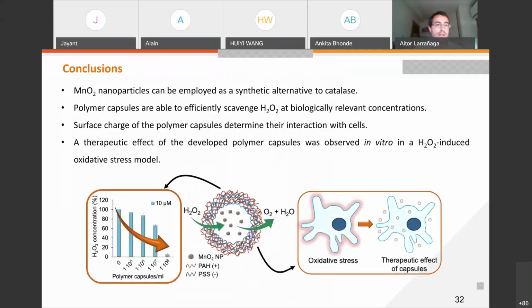So from this example, we can conclude that manganese dioxide nanoparticles can be used as a synthetic alternative to naturally occurring enzymes, such as catalases. These polymer capsules are able to efficiently scavenge hydrogen peroxide at biologically relevant concentrations. And we also found that the surface charge of the polymer capsules will determine the interaction with cells. Remember that positively charged capsules had strong interaction with the cells, but they also promote a more cytotoxic effect. Finally, we found in an in vitro H2O2-induced oxidative stress model some therapeutic effect of our polymer capsules.